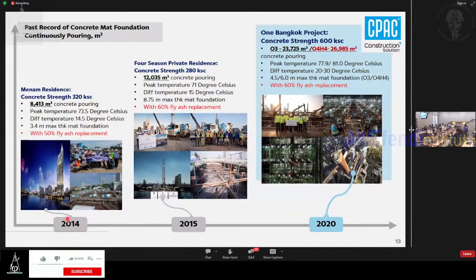You can see here, from 2014 to 2020, these are the mat foundations that we have done so far, using high volume fly ash and pouring continuously in one time. The first one has a volume of around 8,000 cubic meters with the strength here. We replace cement with fly ash at around 50%. You can see the temperature numbers here and the thickness of the structure; the first one is around 3.4 meters.